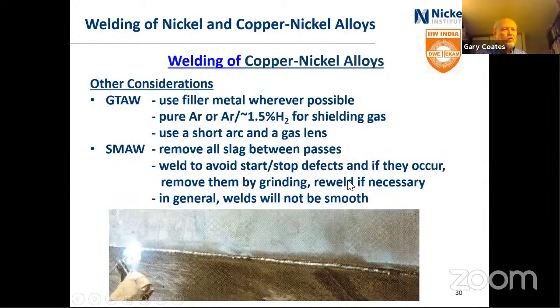So TIG welding, use filler metal wherever possible. Obviously, if you're dealing with 1 millimeter thick material, it may not be easy to use filler metal, may not be required, but in most cases, use filler metal, pure argon. Some people will add a little bit of hydrogen to the shielding gas. Again, the hydrogen is there to take out any oxygen or carbon dioxide, which might break down during the welding in the arc there. That's not a problem for the copper nickel alloys. You don't want to use it in a lot of other materials, but okay for the copper nickel alloys.